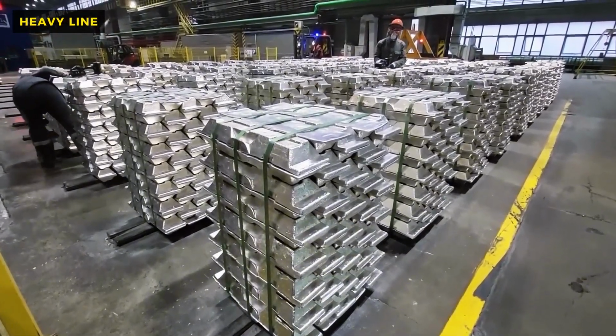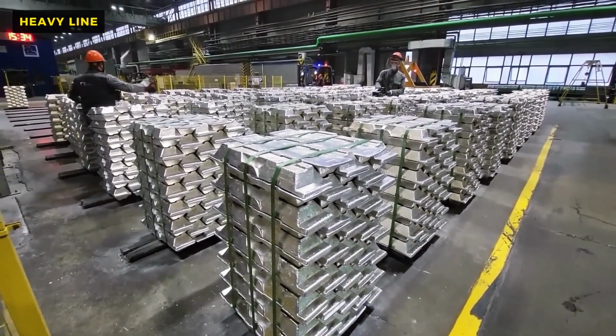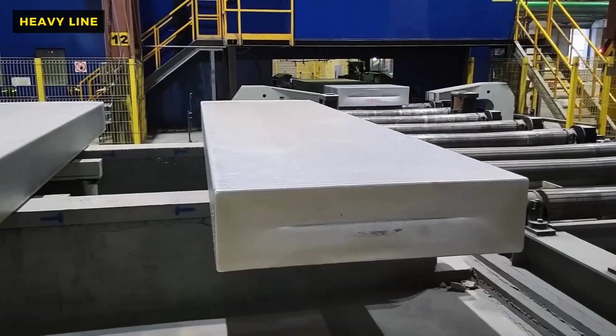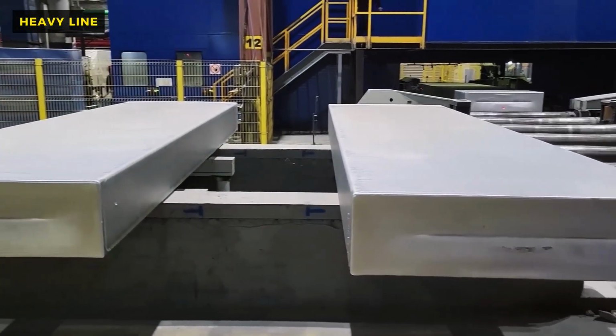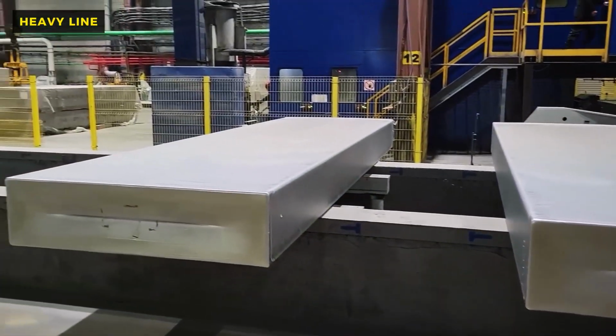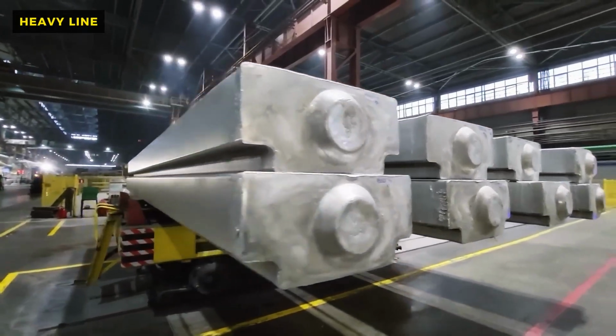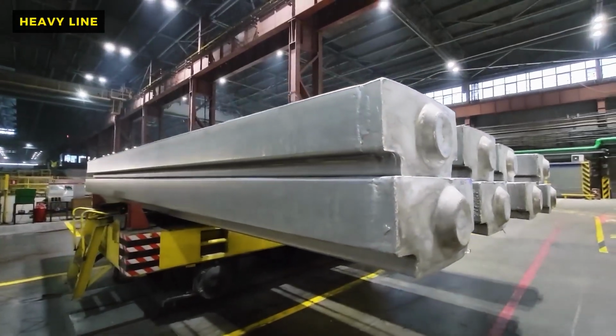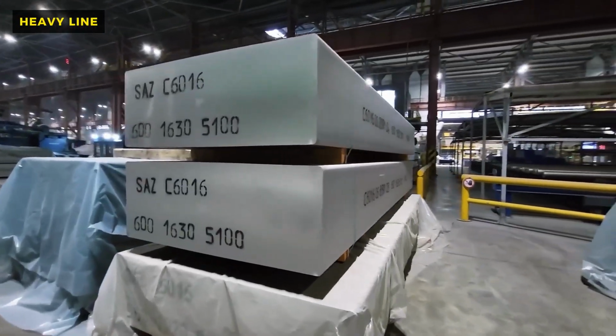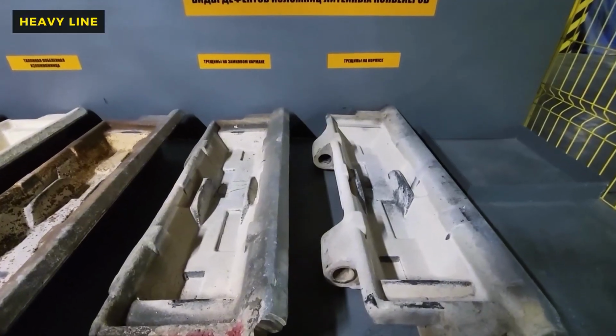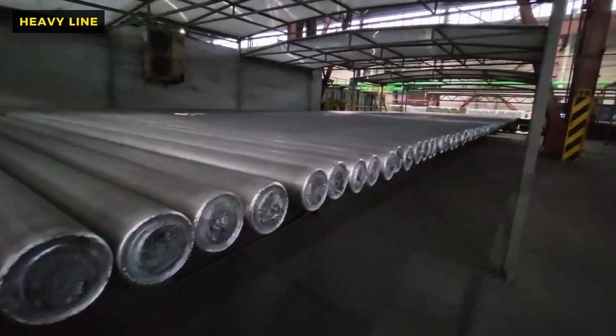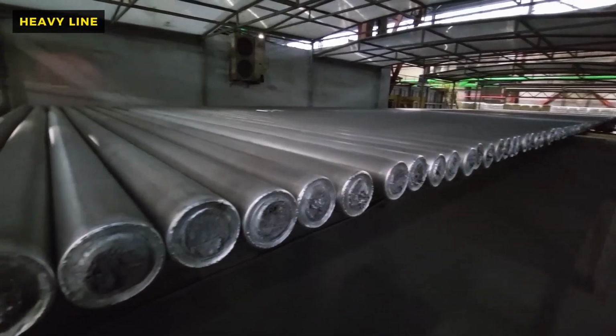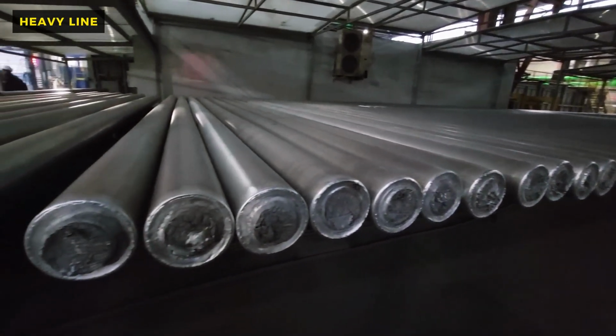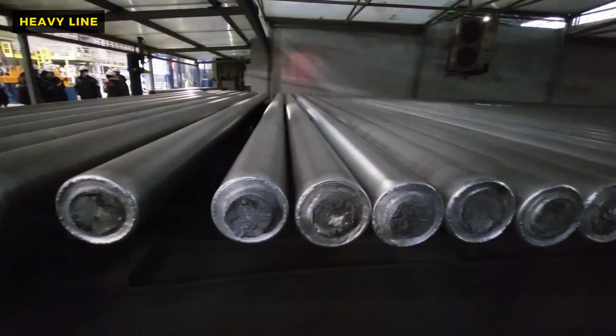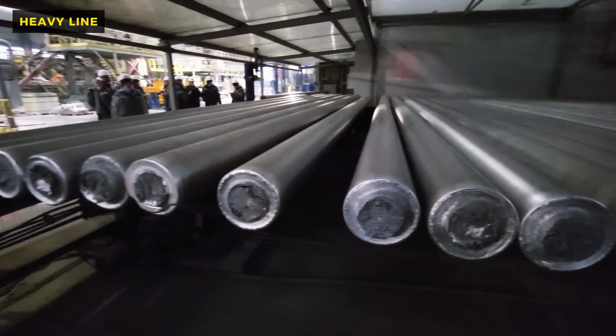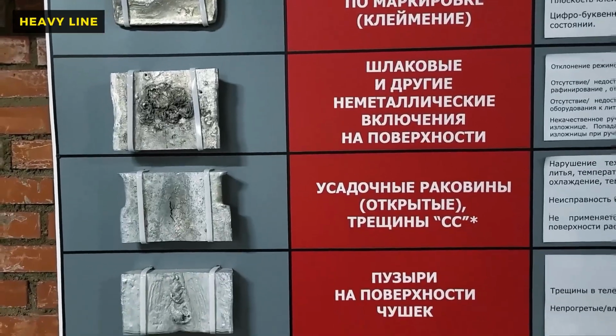The crucible, now filled with several tons of liquid metal, is transported to the cast house, the third major component of the smelter complex. Here, the raw aluminum is poured into holding furnaces where it can be alloyed with small amounts of magnesium, silicon, or manganese to give it specific properties: strength for construction, flexibility for foil, or heat resistance for engine blocks. The atmosphere in the cast house is different again. It is cleaner, brighter, but filled with the perilous beauty of flowing metal.